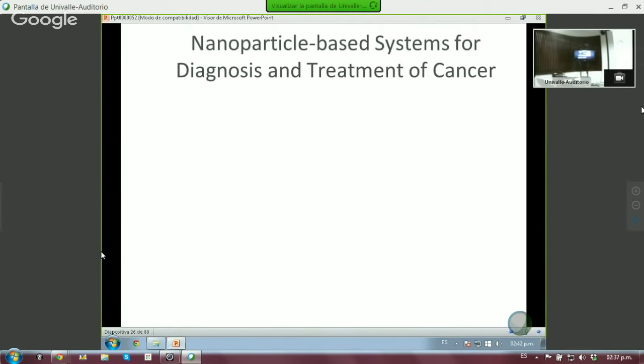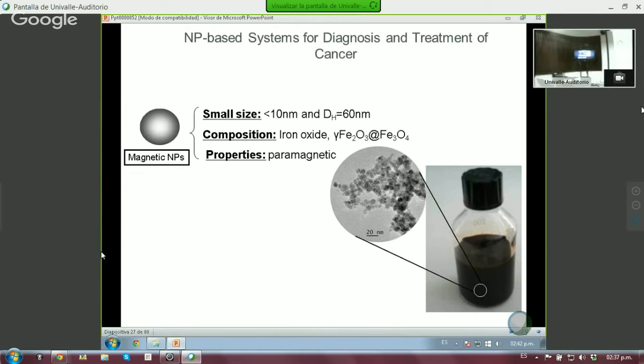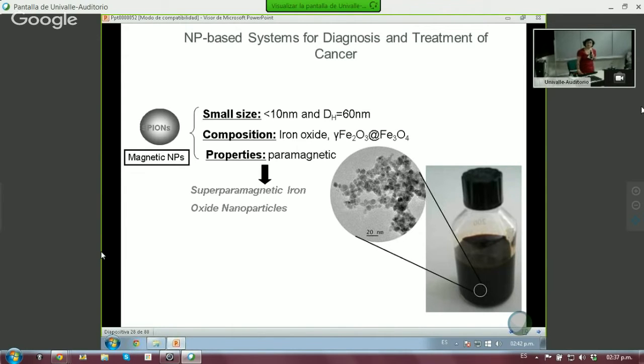Okay, so what we did is we focused on iron oxide. And as you may know, iron oxide is quite a complicated material because the iron has several valences, and then you have several forms of the iron oxide. But what we tried to do is focus on the properties of paramagnetism, and we aimed at having superparamagnetic iron oxide nanoparticles. It's a shame you don't see this here. Actually, what's present is a black liquid, and then you put a small magnet. By moving the magnet, the liquid moves up with it, which is kind of nice, right? So we always like to show it.